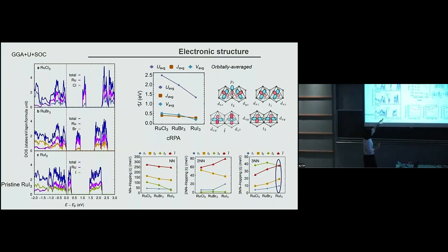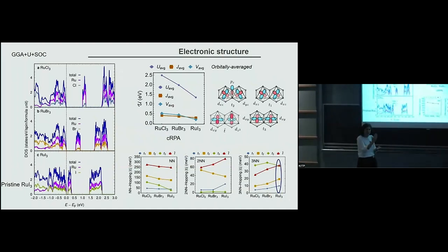These interactions, what I'm showing over there, are all calculated from DFT, so you do constrained RPA. Therefore, I'm following a protocol, and since the values for chlorine and bromine reproduce the gaps that we know about this system, I'm rather confident that the U value that I'm showing, and therefore this gap, is not being falsified because I'm using too large a U. The U's are all obtained ab initio following the same protocol. And as soon as you open a gap, then again, you can talk about these localized states.